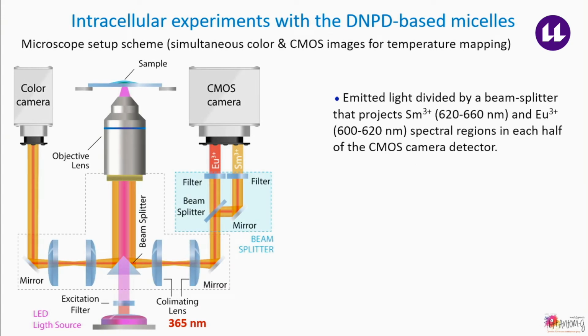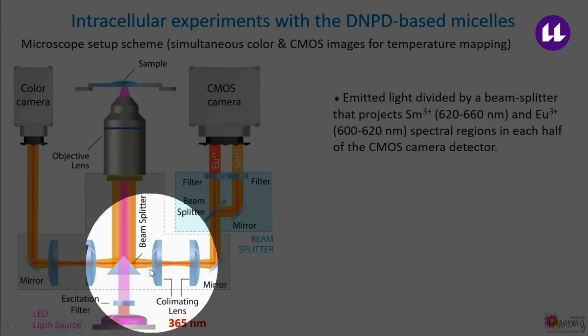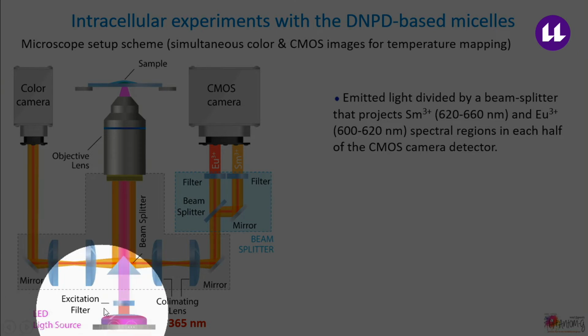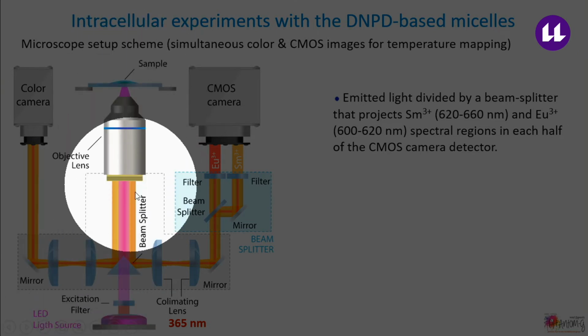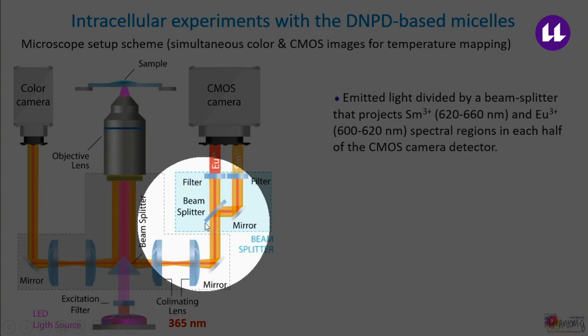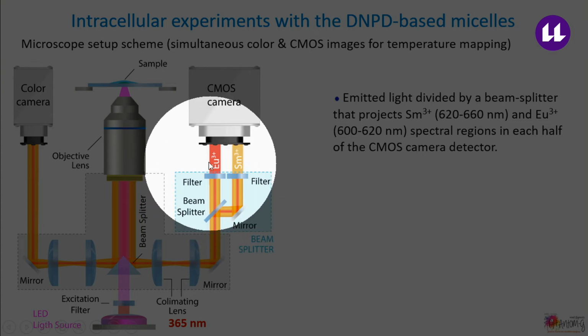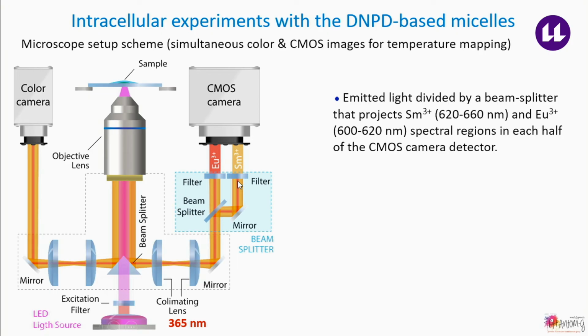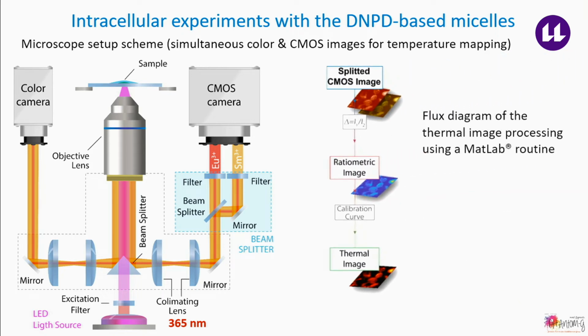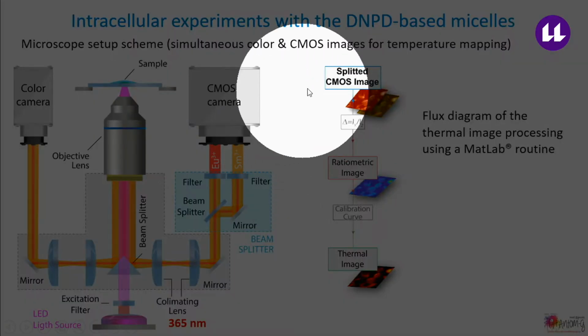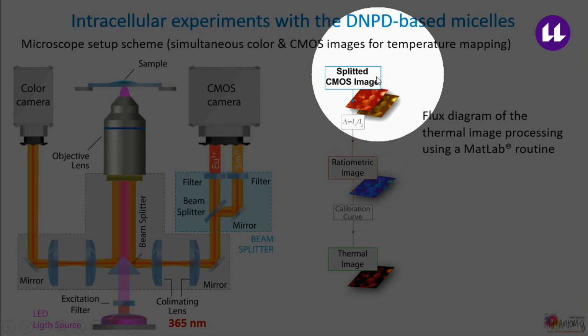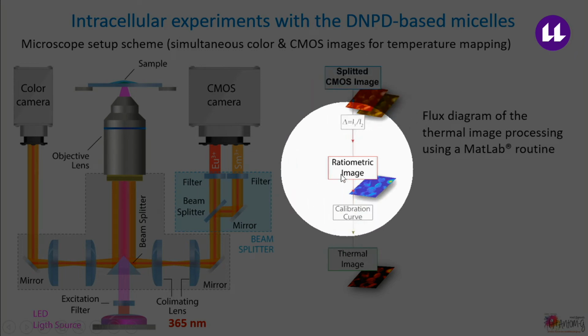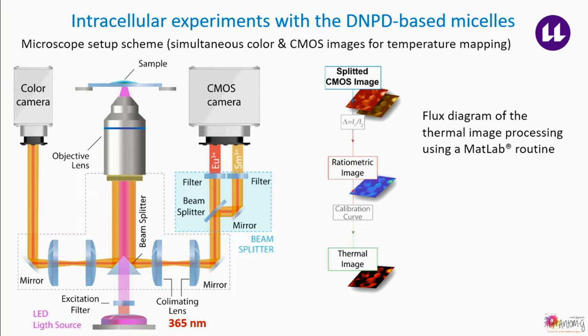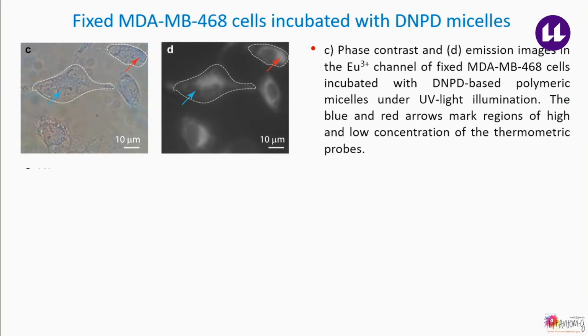With this setup, we use a light-emitting diode to irradiate the sample, and then we collect the emission of the sample and divide that emission in two channels, one the europium channel and the second one the samarium channel. We use the two filters that I mentioned previously to separate the emissions. Then, using a flux diagram that analyzes the two images, the europium channel and the samarium channel, we construct a ratiometric image, and then we apply the calibration curve and have the thermal image.